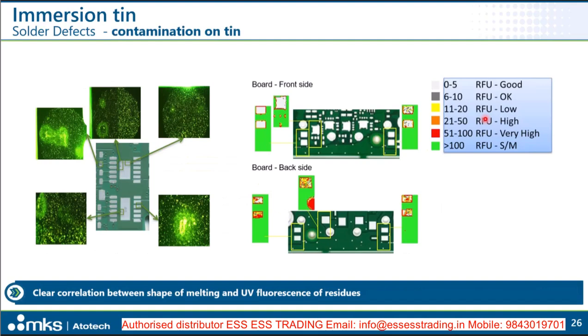We did some further studies to also try to correlate the defect areas with organic contaminations, and that worked well with investigating defect panels with UV fluorescence microscopy, because there we were able to visualize the organic contaminants which are UV active, which otherwise cannot be detected with the bare eye or with microscopy. And what we could really see is that in the areas which appear dark and show some self-dewetting, high concentrations or high values of UV fluorescence could be observed. So it was possible to correlate the organic contaminants to these defect dark areas of the immersion tin.